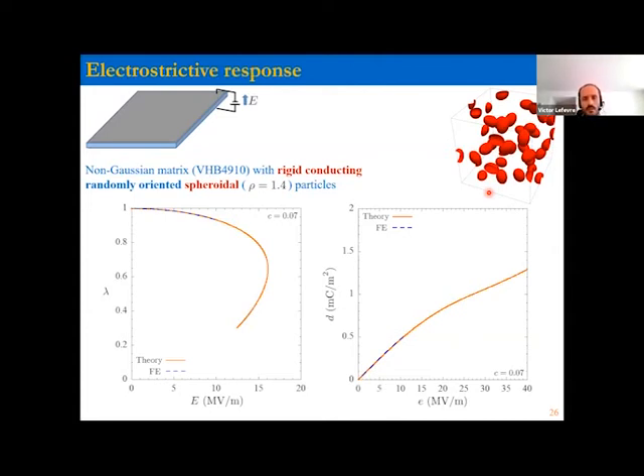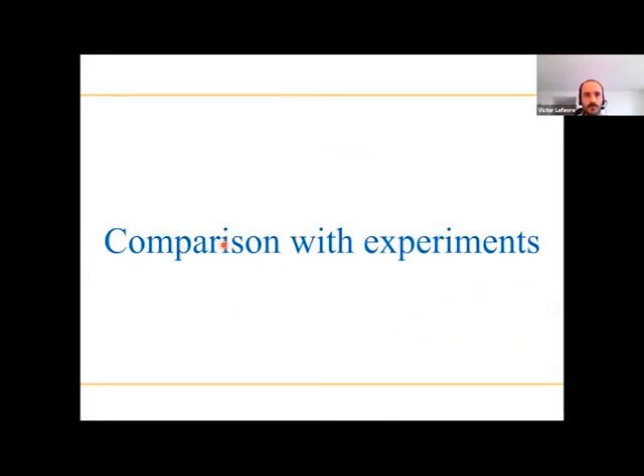So we computed ahead of time all the parameters that come in the formula. And then this is a true comparison between the prediction of the model in orange and the numerics in blue. This is not a fit. It's a real prediction and comparison between these two sets of results. So good agreement between the two.